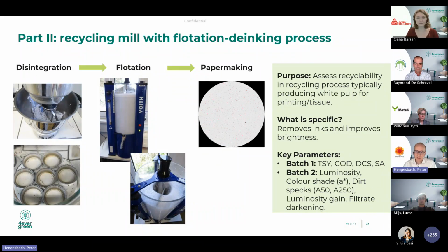So what is very similar, as you have already heard in the first part, is the approach of looking at the repulping behavior. But the specific thing here for the flotation deinking process is that those recycling processes typically use high consistency pulping stages. That means higher consistency conditions, meaning a lower dilution in the repulping stages, which is significantly different compared to the conventional process.